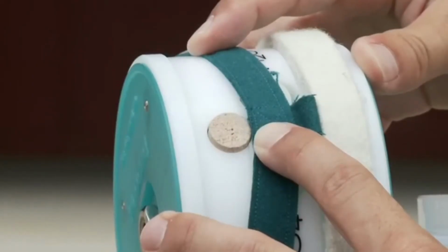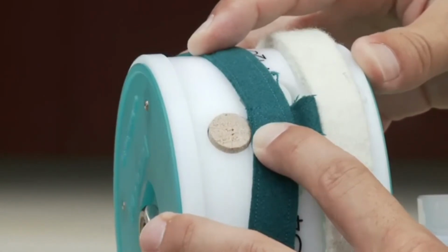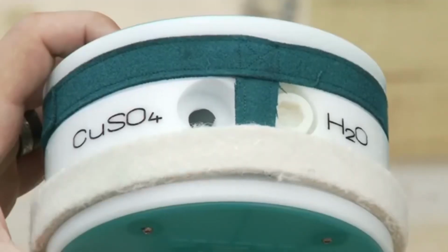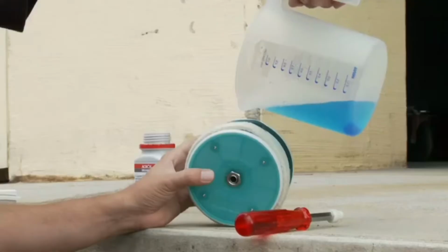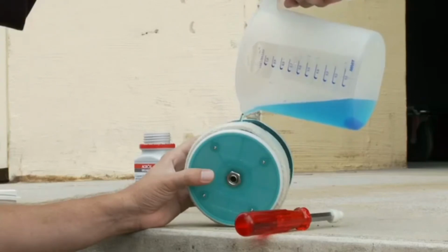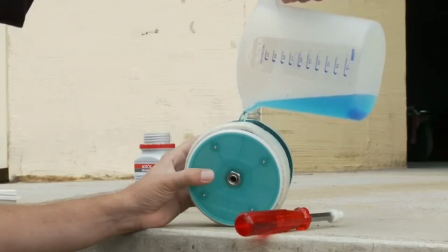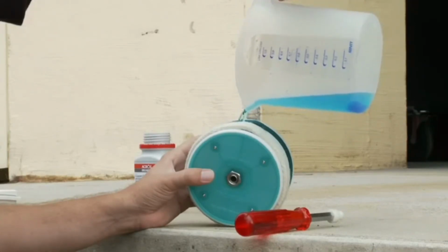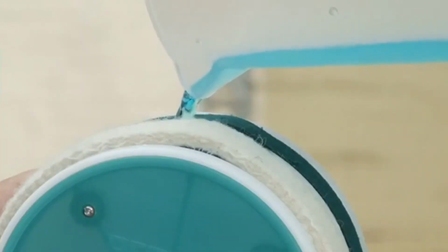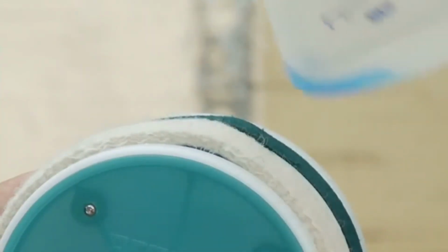The felt hoops and the felt hoop connector should be saturated with water to ensure a low resistivity contact before measuring. The electrode should be filled as completely as possible with a minimum of air in the compartment. And in order to ensure that the solution remains saturated, add an additional teaspoonful of copper sulfate crystals into the electrode.